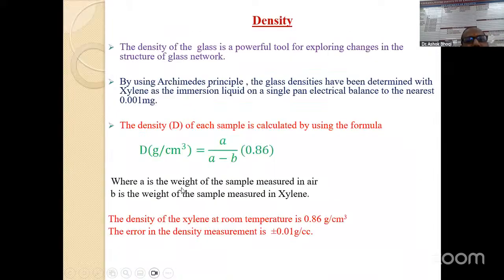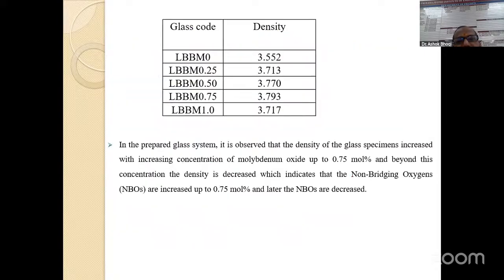Coming to density, the density of the prepared glass samples has been measured with the help of Archimedes principle, A by A minus B into 0.86 gram per cc. These are the density values of the prepared glass samples. The density values increase with increasing the concentration of molybdenum up to 0.75 mole percentage, and later the density value is observed to decrease. It means that the non-bridging oxygens are increased up to 0.75 mole percentage, and later the NBOs are decreased.